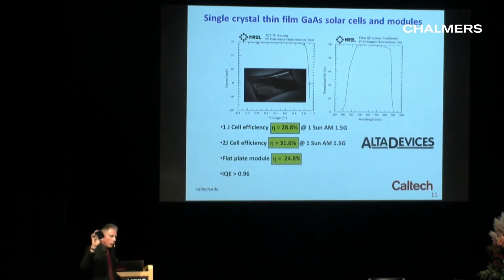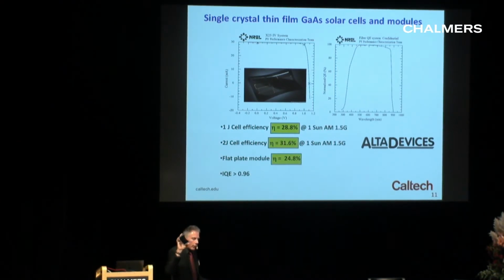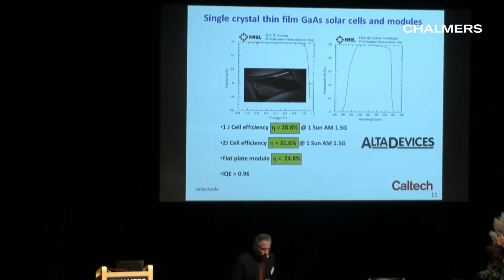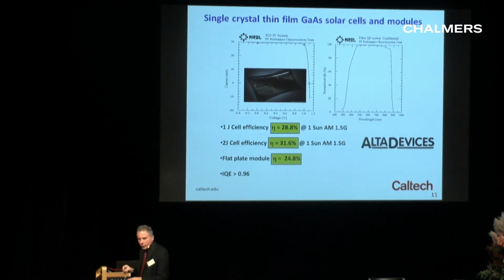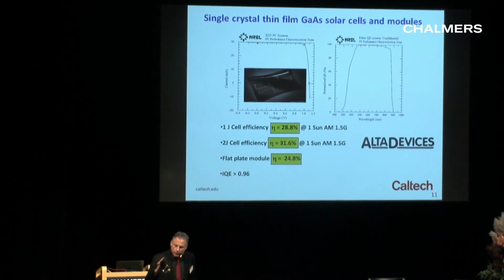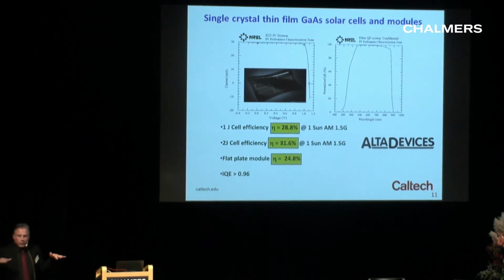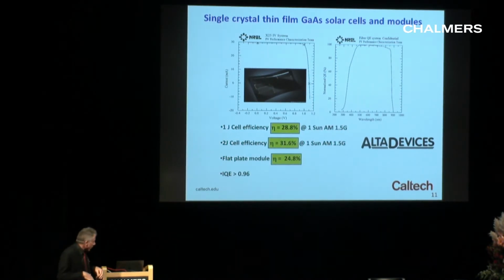So this is a single crystal, 28% efficient gallium arsenide solar cell. As you can see, it's flexible. So I'll give it to Bengt, and he can verify that it's flexible. We can also gang these together in series parallel combinations and make flexible modules, so you can get whatever voltage or current you like. And you can see on the backside there's a metal film, and that's acting as a mirror. Also, the semiconductor is a brittle material, and it would fall apart and break if it weren't held in compression carefully. And that compressive stress makes the material very durable.